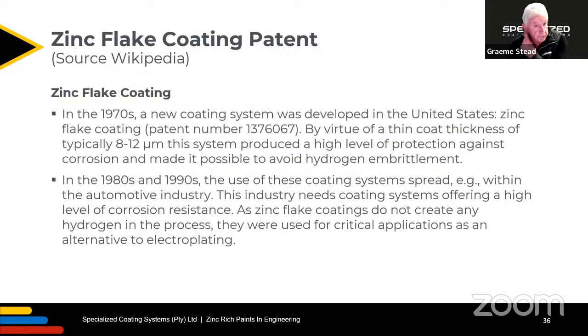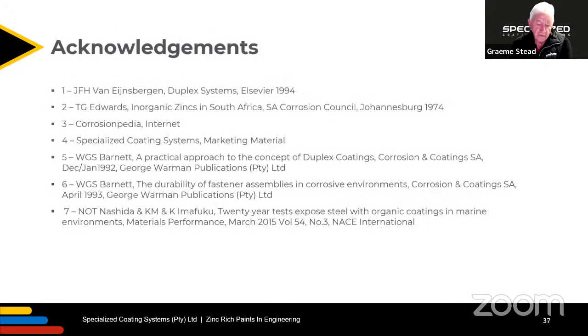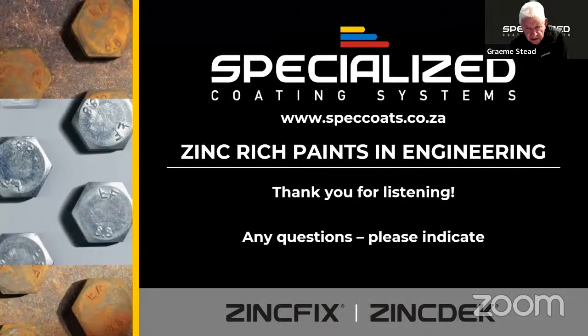And this is the patent mentioned with the thin film thickness of 8 to 12 microns. And the zinc flake coatings do not create any hydrogen in the process. They were used for critical applications and as an alternative to electroplating. So these are developments with zinc coatings that are going on all the time. It's a very big subject, and we could go on talking for some time further. Those are my acknowledgements, and I thank you for listening. And if there are any questions, please indicate.